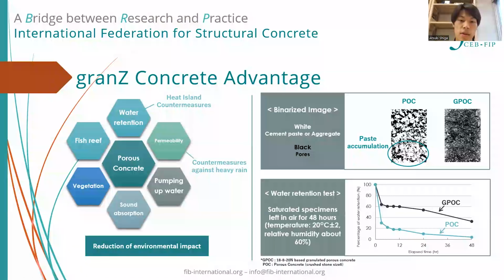And in the case of our POC, cement flow and compaction strengths are just optimized for the bond condition. The following binary images of each cross-section of normal POC and granulated porous concrete show that the voids are unbalanced in the upper layers. It also shows that the POC-specific problem of cement paste dropping does not occur with granulated porous concrete.